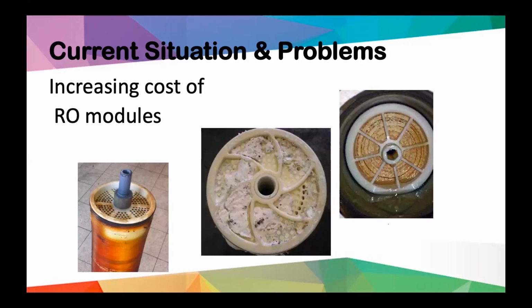This may also be a great drawback of the fouling, because we are using different hard washing techniques which go through the layers of the membranes, make some scratches, and make some deformation of the polyamide layer. This decreases the efficiency of the membrane day by day, until all the sheets of the membrane are lost and the membrane fails. As you can see from the middle photo, there are hard scales of fouling: inorganic salts, some scales of iron, and some waste, which is deposited on the spiral wound sheets of the membranes.